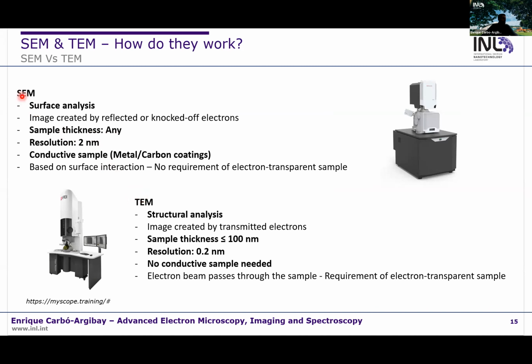Let's say SEM is a technique where we have a scan electron beam scanning the surface of the sample. We don't have any requirement in terms of thickness. Independently of the thickness of the sample, we can analyze it. We just need to make the sample conductive, and the resolution is 1 or 2 nanometers.